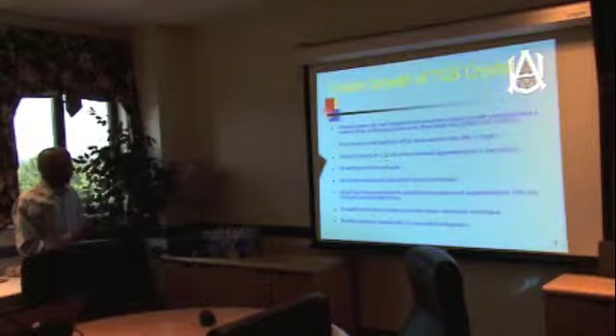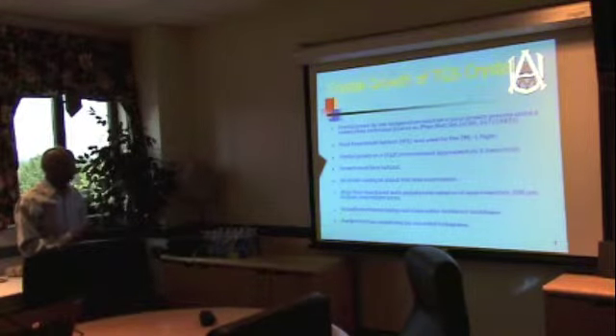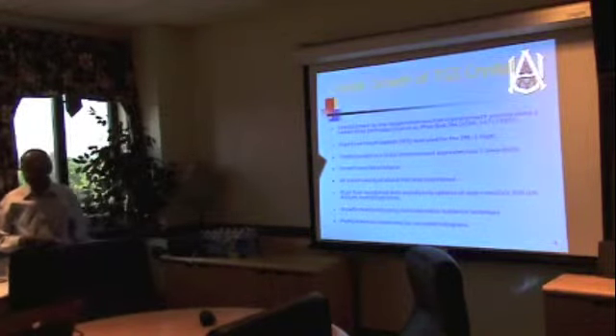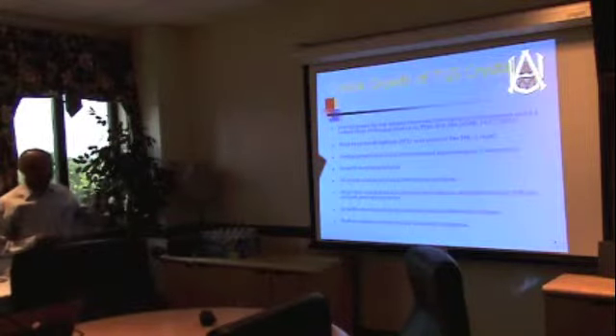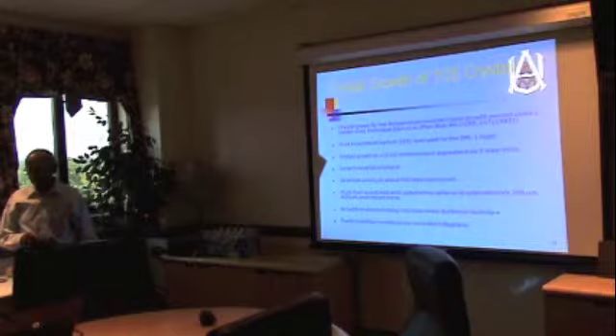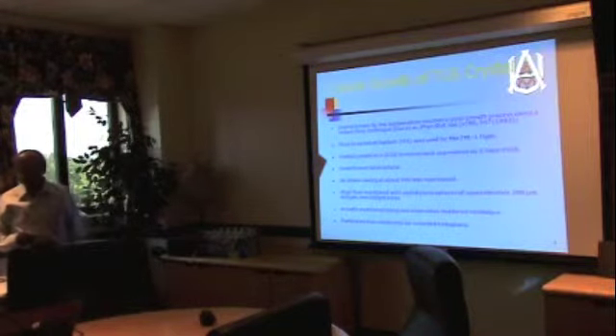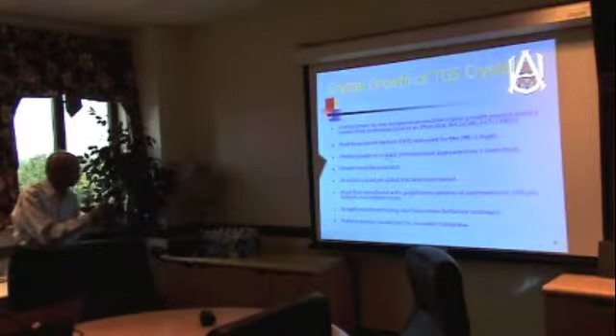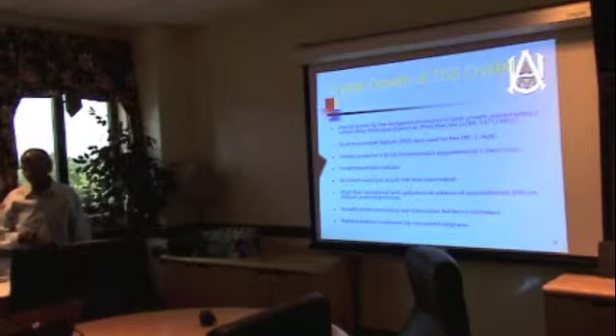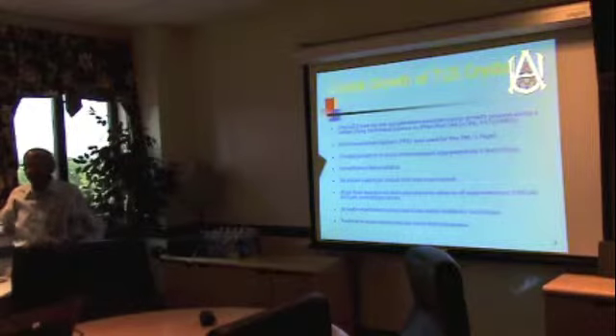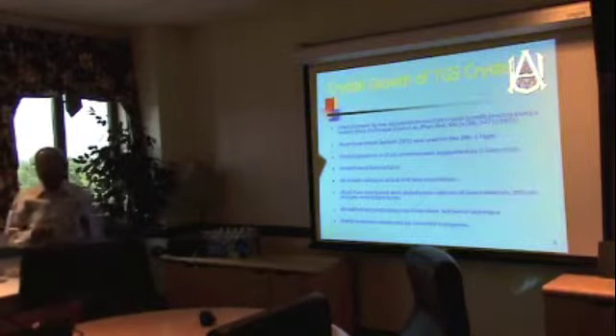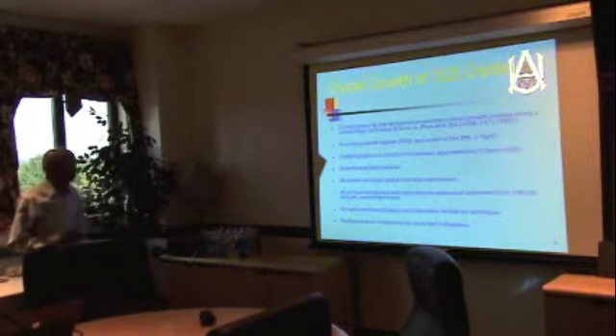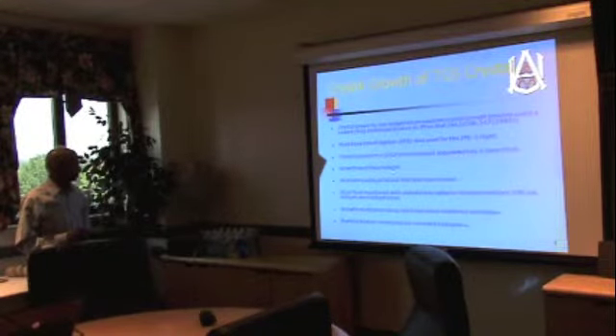The crystals were grown on the 010 oriented seed. And you might ask why did we choose this. Because this is the fastest growing phase of TGS crystal. If you look at the crystal morphology. There are many phases. This is a monoclinic crystal. So this crystal has 010 phase oriented phase in the fastest growing. And since the time of the shuttle is only about 6 days, we wanted to use the phase which is fastest growing. And incidentally it also happens that this is the phase on which detectors are fabricated. So we thought that once we grow a crystal on this phase, I don't have to do polishing, cutting, nothing. We can just fabricate detector right on the surface. So we choose this. And this was different than space lab 3. We did not use 010 in space lab 3.